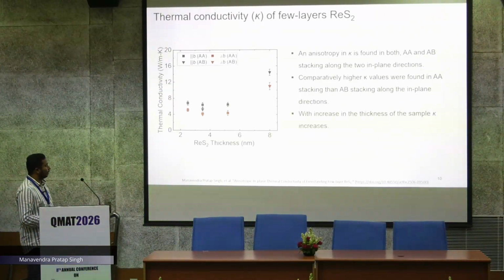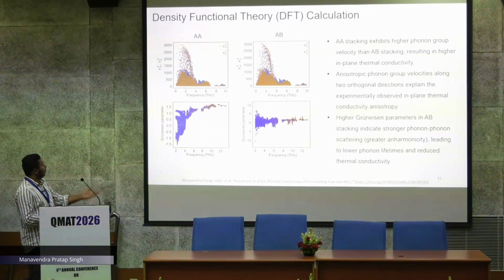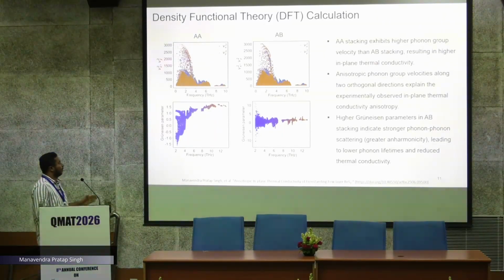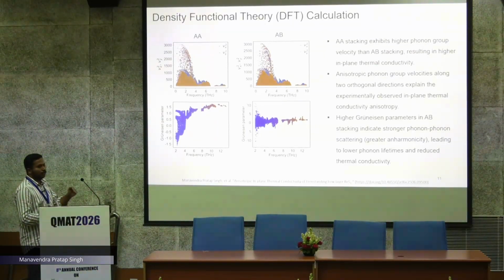compared to AB stacking. With increase in thickness we can see the in-plane thermal conductivity increasing, but anisotropy is maintained. For the experimental values we have some theoretical support from our collaborators, and we can see the calculated phonon velocities are different in different orthogonal directions, so anisotropy is maintained, and we can see in AA and AB also the difference in anisotropic phonon group velocity.